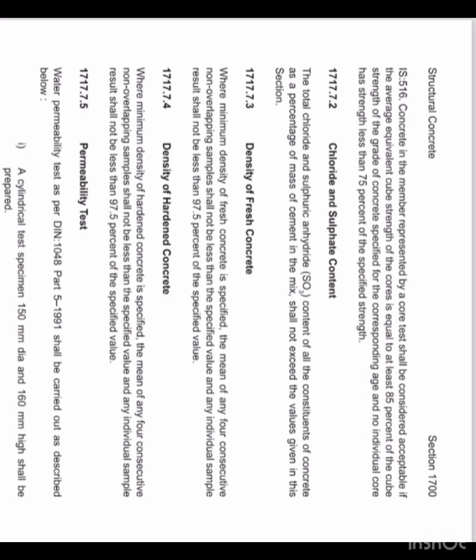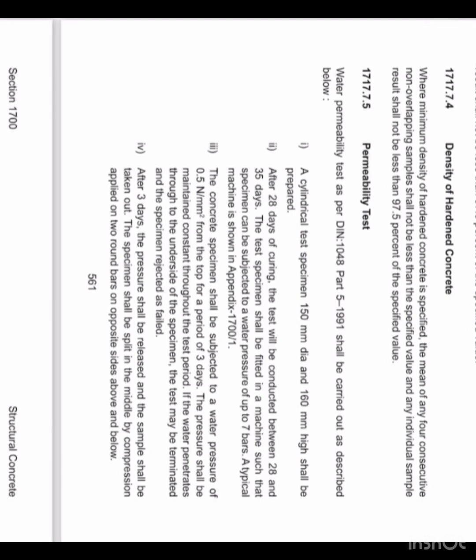Density of fresh concrete. Where minimum density of fresh concrete is specified, the mean of any 4 consecutive non-overlapping samples shall not be less than the specified value, and any individual sample result shall not be less than 97.5% of the specified value. Density of hardened concrete. Where minimum density of hardened concrete is specified, the mean of any 4 consecutive non-overlapping samples shall not be less than the specified value, and any individual sample result shall not be less than 97.5% of the specified value.